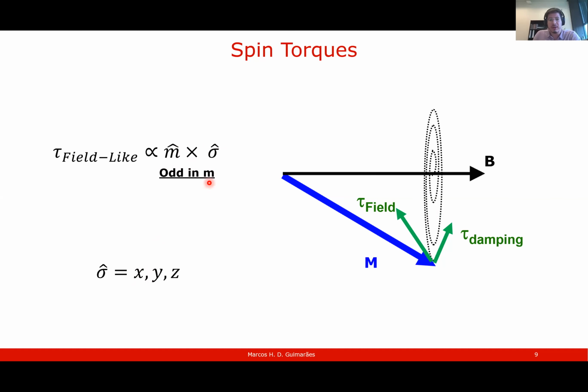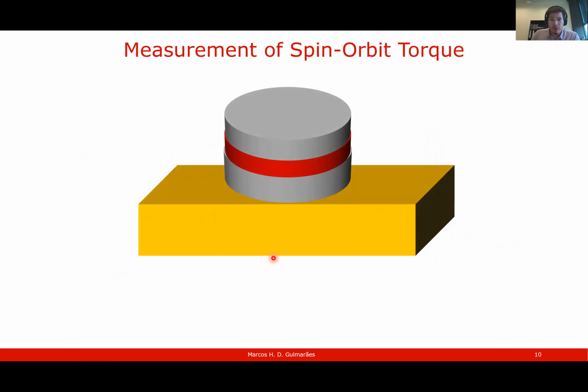And very important here to keep in mind is that this type of torque is odd in the magnetization direction. So this means that if we change the magnetization, go from plus m to minus m, the torque also changes sign. The second term here, which is this damping torque or damping-like torque, is even in the magnetization direction. So if we change m to minus m, the torque doesn't change sign. And it's given by m cross sigma cross m. Sigma here is x, y, z, the direction of the field. So let's say x again, so m cross x cross m.